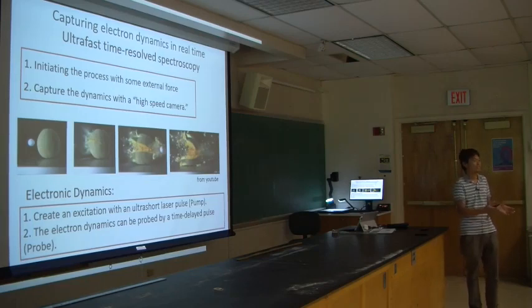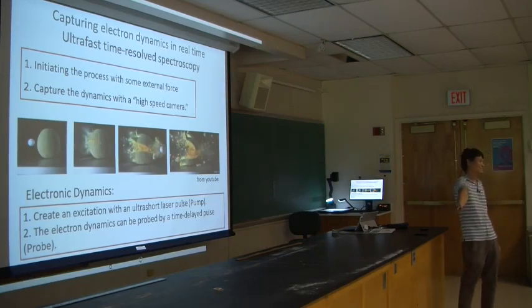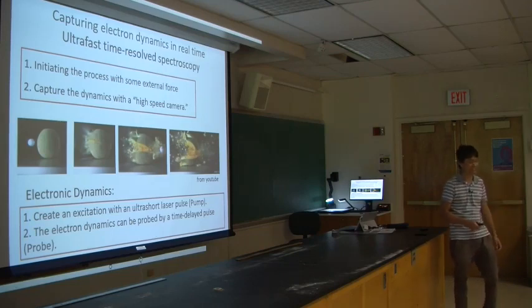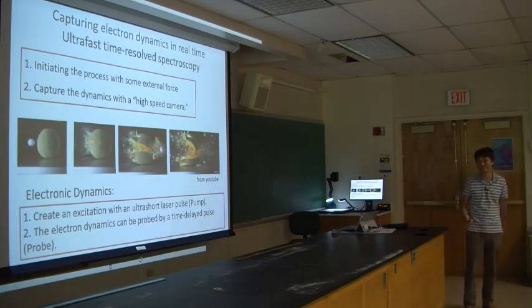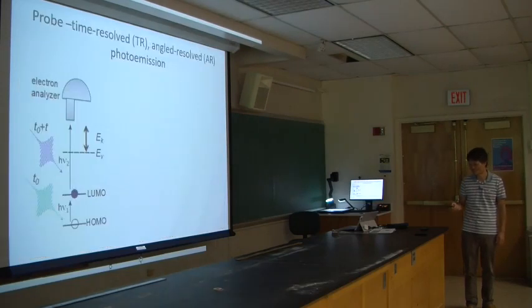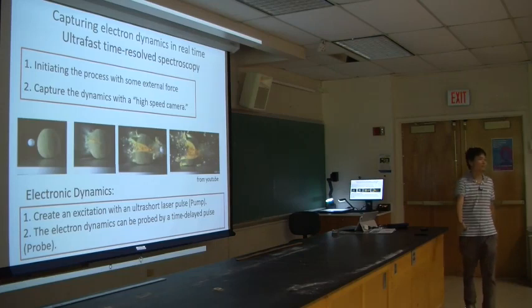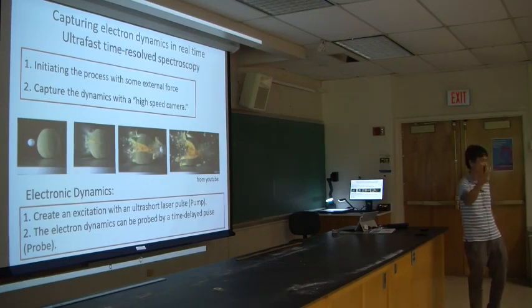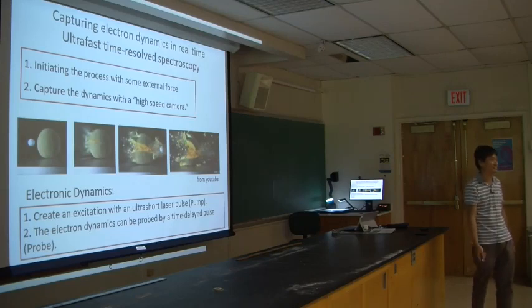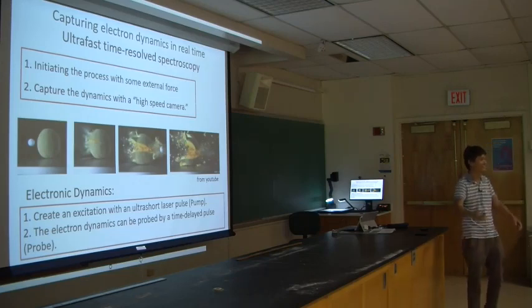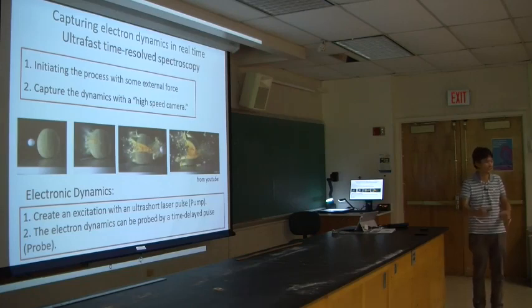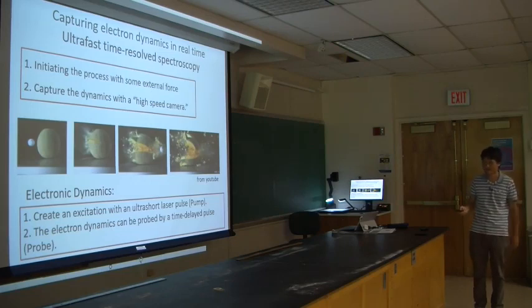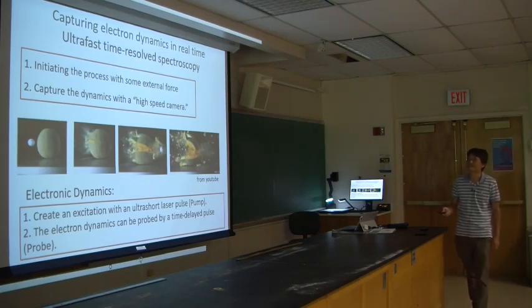What we do is we have these femtosecond laser pulses, right? We have one pulse that excites the solid, and then another pulse comes in later to probe what's happening after the initial excitation. This is what we call a pump-probe experiment. Of course there are different variations for the probe. You can probe the optical properties, or in our case, we usually do so-called photoemission. We ionize the excited electron and see what electronic state it comes to after some controlled delay time from the pump event, right?